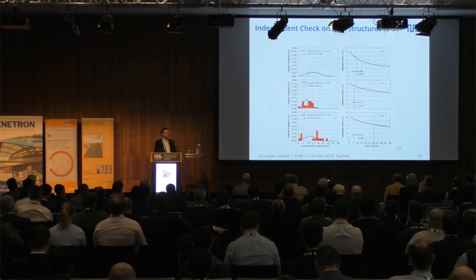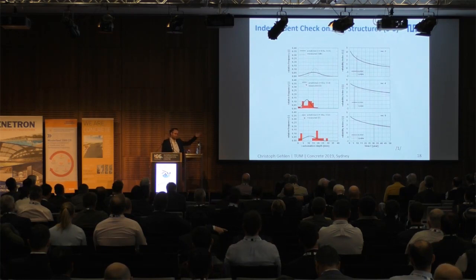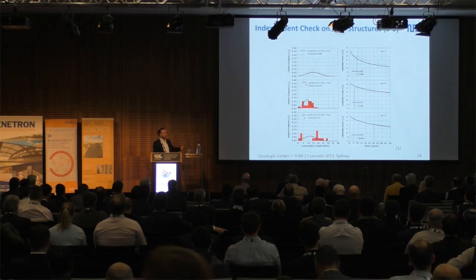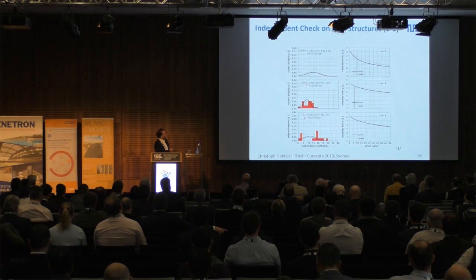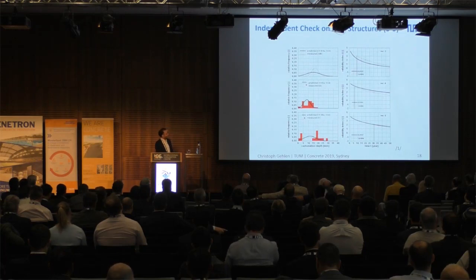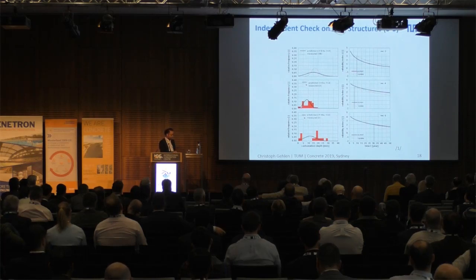So we got all the information of the structures, as I've shown you in the table. We did our calculation, and later on we got real carbonation measurements. And as you can see here, predicted carbonation depths and measured are more or less comparable. And this means that the updated reliability of your structure is more or less in line with what was predicted beforehand. So one can say the models just work.